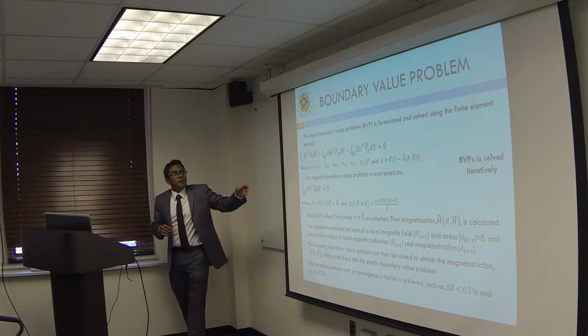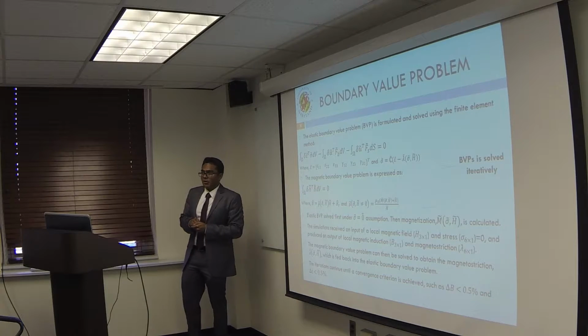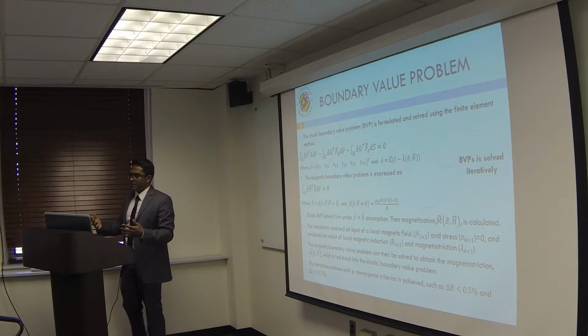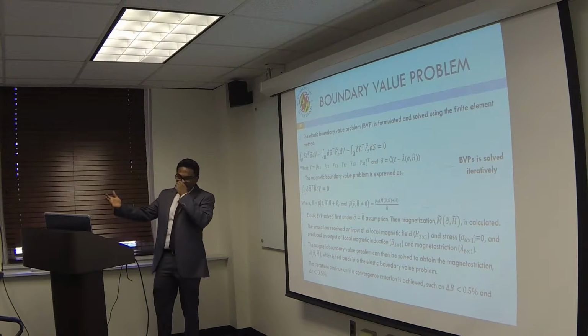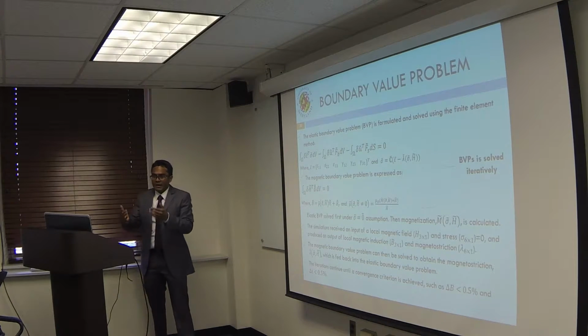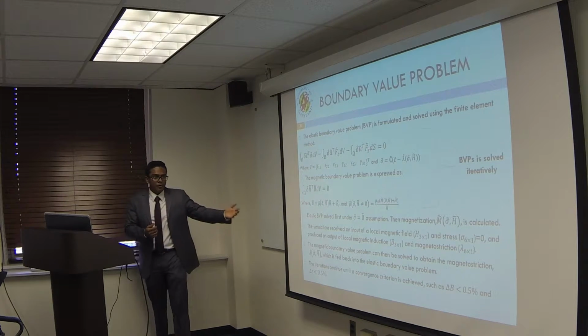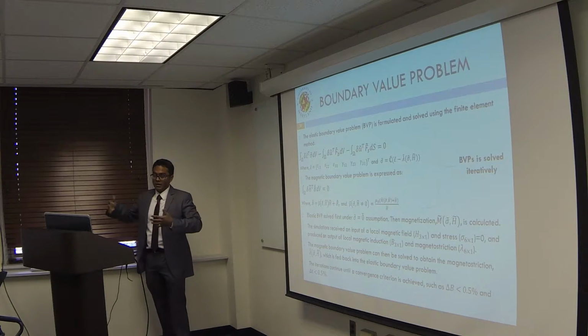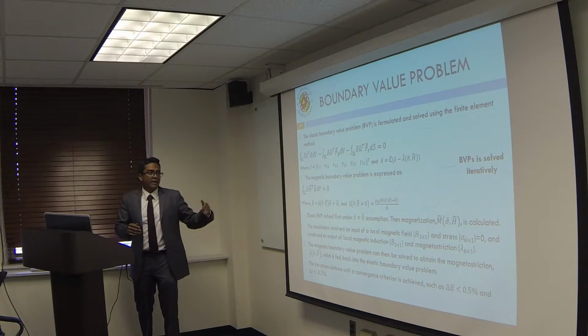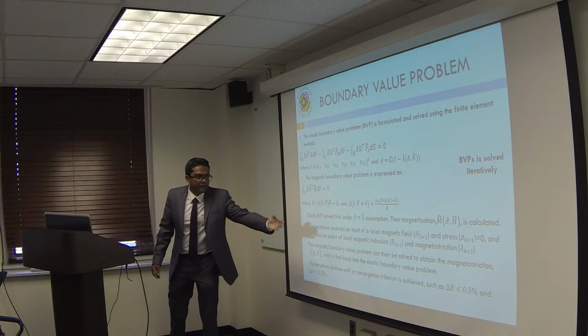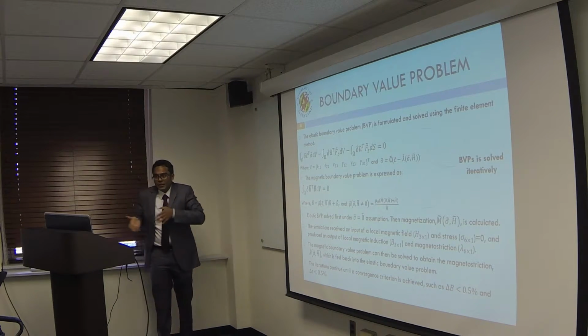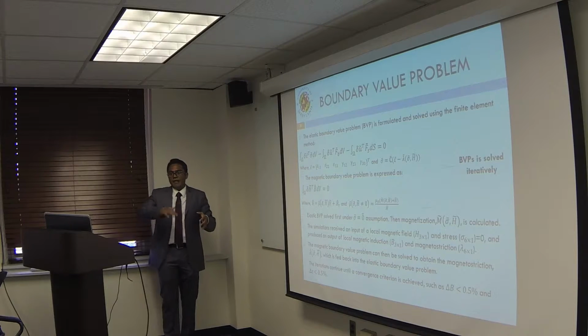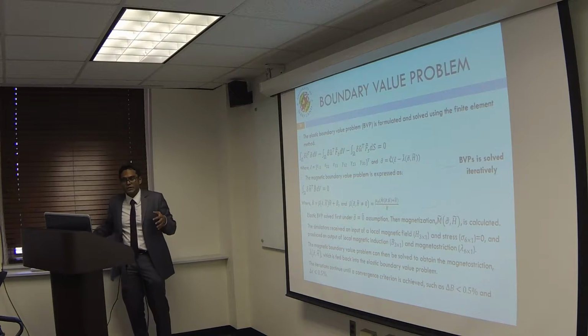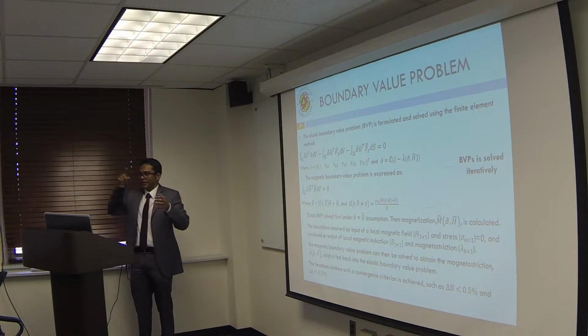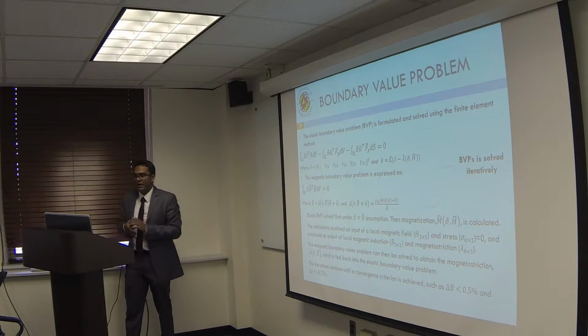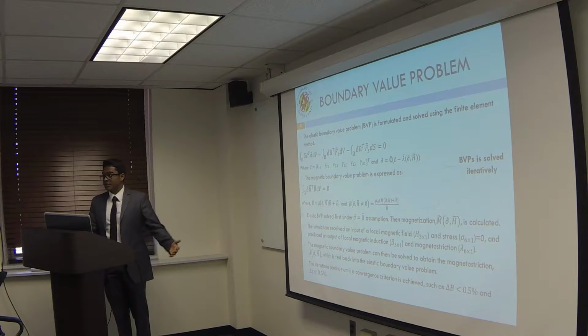So we have the elastic boundary value problem, and then we have the magnetic boundary value problem. We start out by assuming that all stresses are 0, and this gives you a value for the magnetization. Now COMSOL receives an input of magnetic field, and in our case, the stress is 0. This produces an output of magnetic induction and magnetostriction, which goes into the magnetic boundary value problem. And the output, which would be magnetostriction, goes into the elastic boundary value problem. This iterative process keeps going on and on until we reach convergence in our solutions.